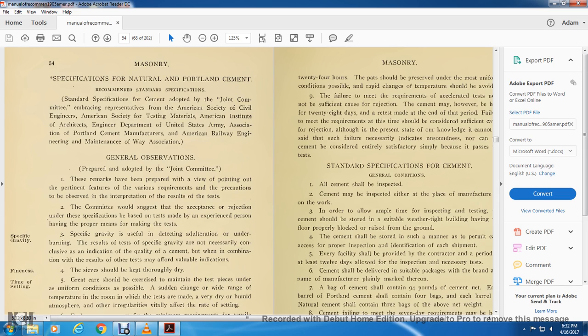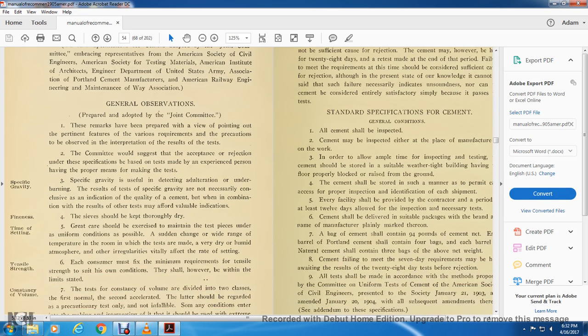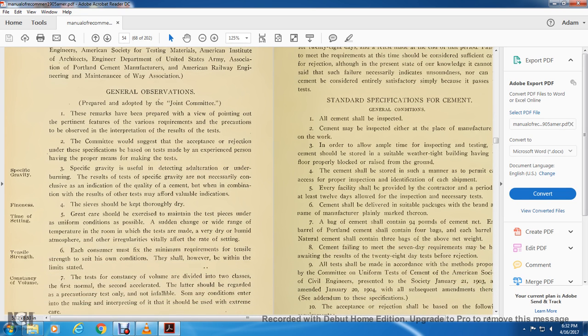The remarks have been prepared with a view to pointing out the pertinent features of the various requirements, of the precautions to be observed, and of the interpretation of the results of the tests. The committee would suggest that acceptance or rejection under the specification be based on tests made by persons having the proper experience and means of making the tests. Specific gravity is useful as a detection of adulteration or underburning, but not necessarily conclusive as an indication of the quality of the cement. In combination with the results of other tests, it may afford a valuable indication.